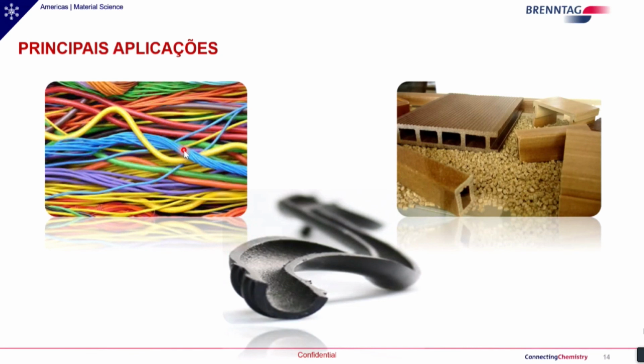The proportion of use relies on the proportion of use of the wood dust. If you are using 30%, you're going to have to use about 1 to 1.5% of agents. But if you have 50% of wood dust, you can go between 1.5 to 2%. Of course, it depends on the polypropylene that is used, on the wood residue that is used. And this allows us to work. The proportions are low, okay?